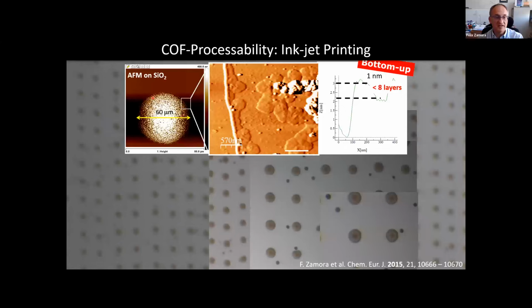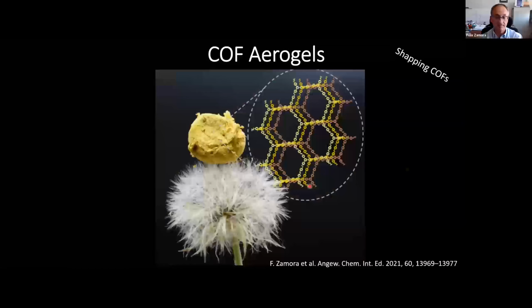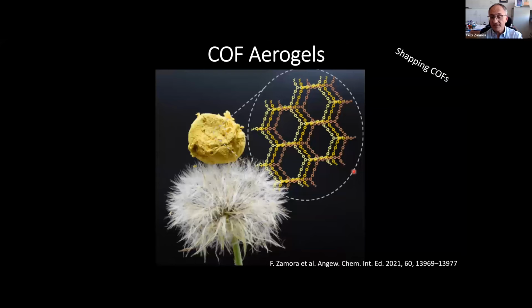So the meaning of that is that these dots are formed by a combination of nanolayers that are aggregated in this dot. But with this experiment, we demonstrate that it is possible to control the deposition of the COFs on different substrates. And this can be useful if you want to use the material that you produce for, for instance, electronics. You need this control. Okay, let me focus on recent results that we produced with these imine-based COF gels. We were working to produce COF aerogels.